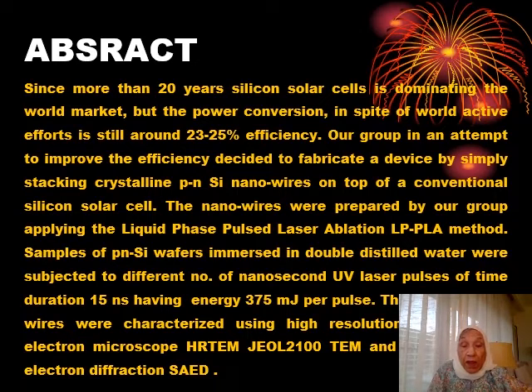We prepared these nanowires by applying the liquid phase pulsed laser ablation method. Samples of the PN silicon wafers immersed in double distilled water were subjected to different numbers of nanosecond UV laser pulses from a nitrogen laser of time duration 15 nanoseconds, having energy of 375 millijoule per pulse. The wires were characterized using a high resolution electron microscope and a JEOL 2100 transmission electron microscope, and to determine whether they are crystalline or not, we used the electron diffraction method.